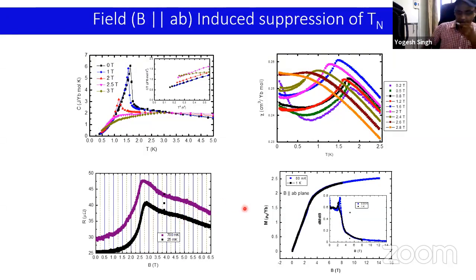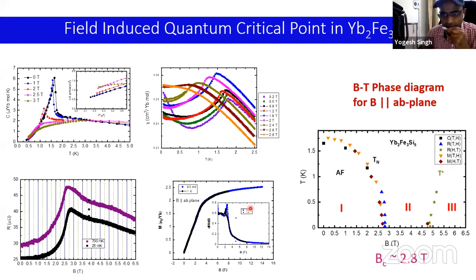So we can start building a phase diagram using these data, and that I have done here. So I show here that the transition temperature, the antiferromagnetic transition temperature, can be continuously tuned and pushed to 0 temperature at a critical field close to 2.8 Tesla. Okay. And these other bumps that I was showing you in various measurements can be plotted here. And this divides the phase diagram into 3 regions, 1, 2, 3. So we would like to find out more about what these regions are.